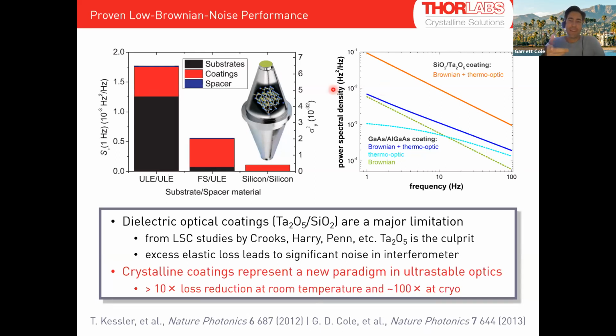So the early cavities were made from ultra low expansion glass spacers, so for zero thermal expansion, and then ultra low expansion end mirror substrates. But it turns out people at the time didn't understand that it was actually the Brownian motion was driven by the high elastic losses. A couple folks noticed this, pointed out you need to push to the lowest elastic loss possible in the materials, change those ULE end substrates out for fused silica, and all of a sudden you have a large drop in noise.